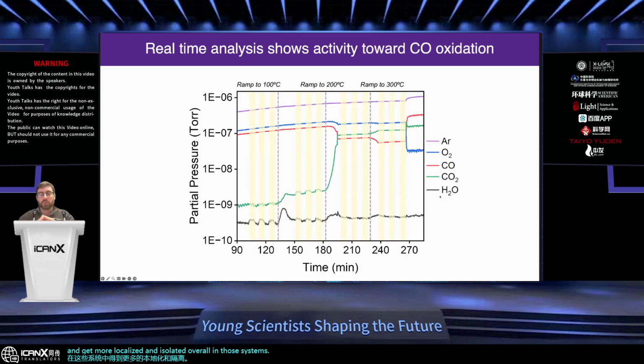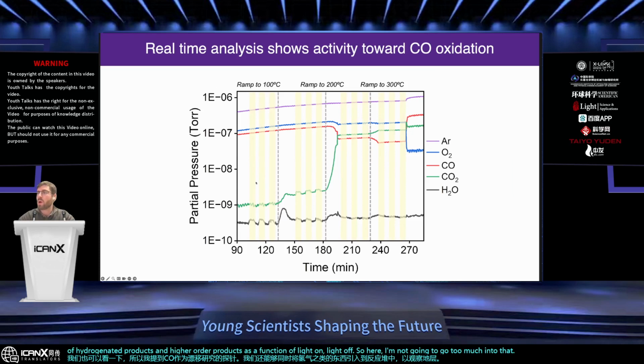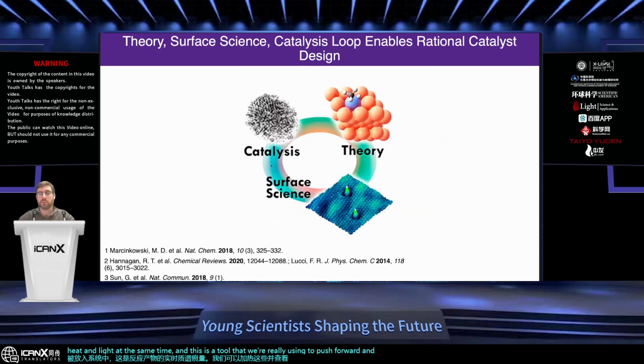We can also look at, so I mentioned CO as a probe for DRIFTS studies. We're also able to introduce things like hydrogen gas into the reactor at the same time to look at the formation of hydrogenated products and higher order products as a function of light on, light off. So here, I'm not going to go too much into this work right now, but wherever you see these yellow bands, that's a laser illumination being put into the system. And this is a real-time mass spectrometry trace of the reaction products that are coming out. We can heat these up and look at the synergies between heat and light at the same time. And this is a tool that we're really using to push forward and understand these systems a little bit better.